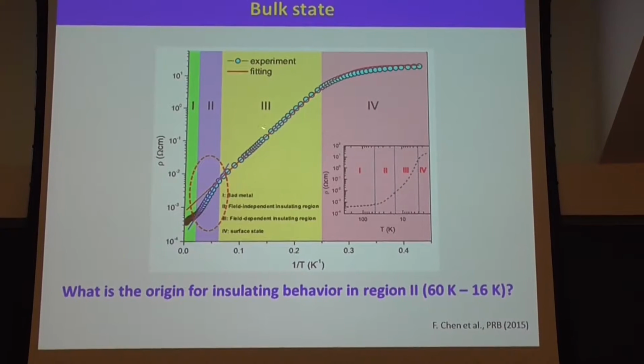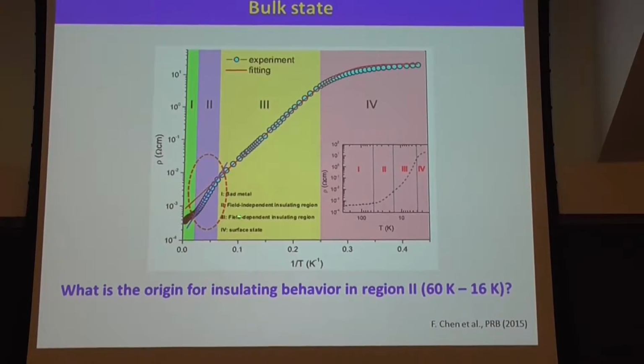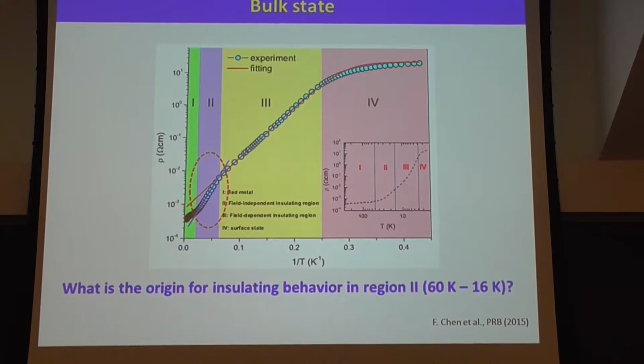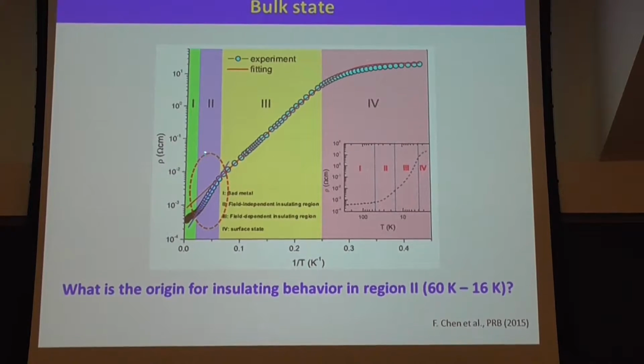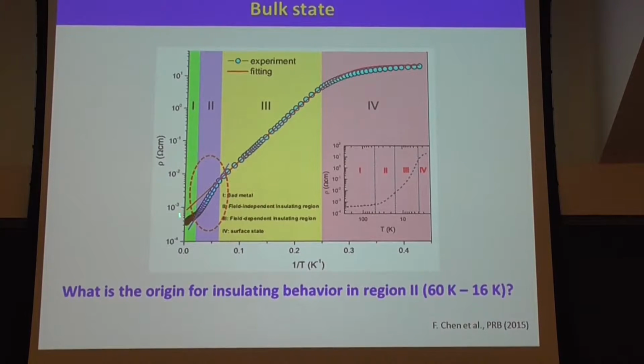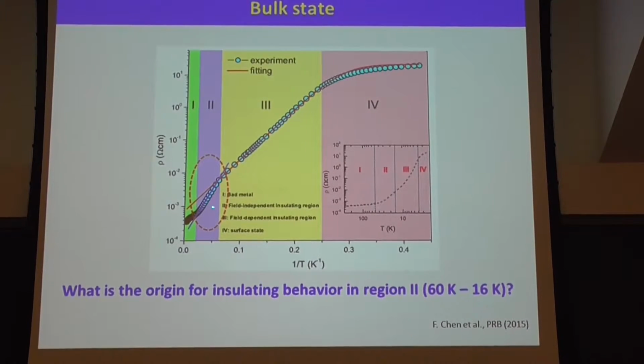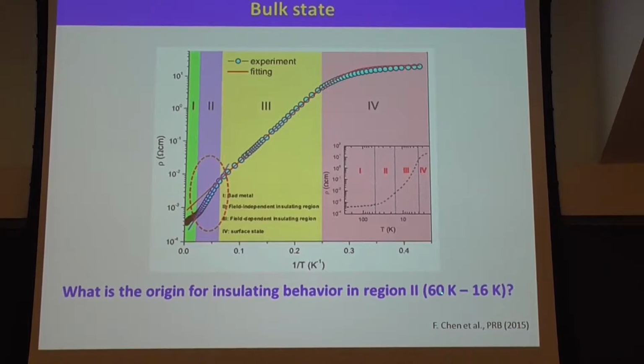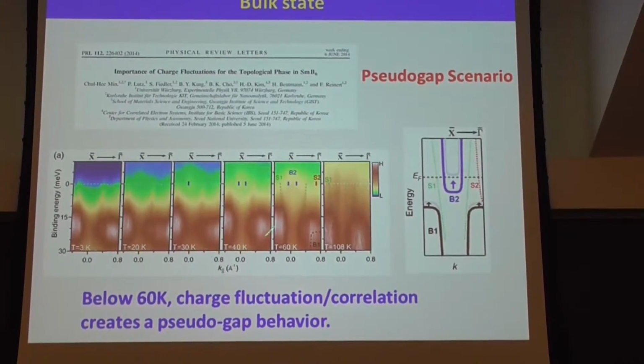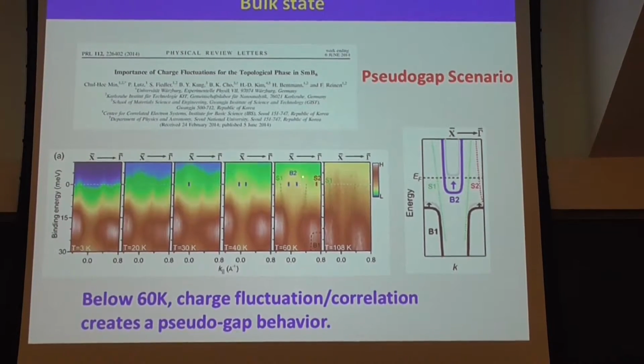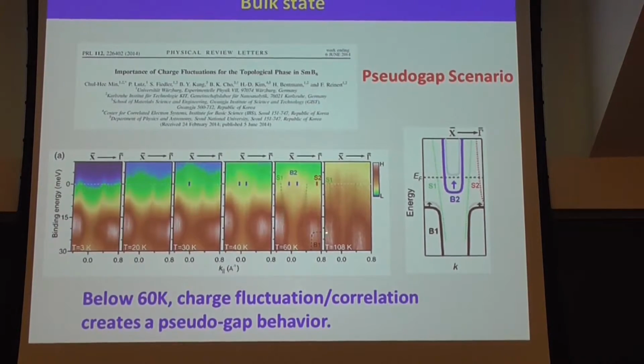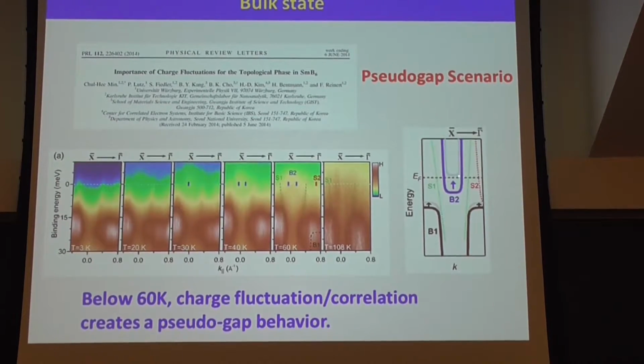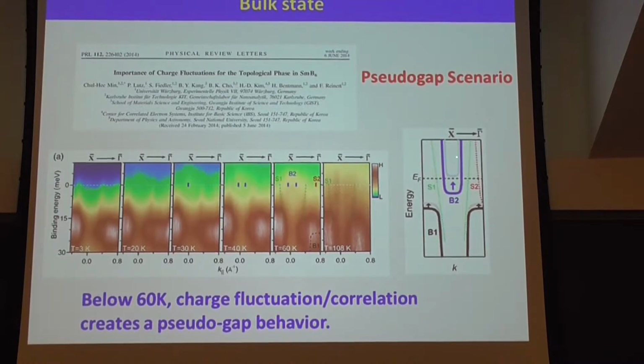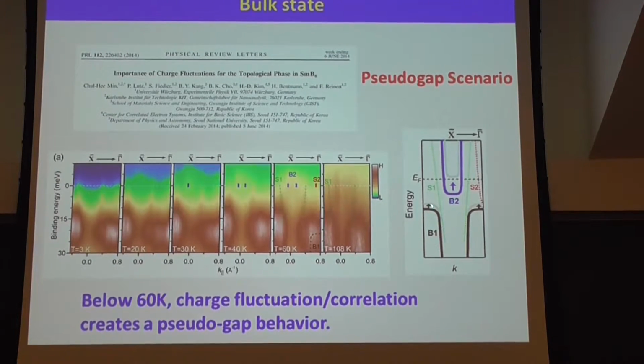But in this region, it means the field-dependent insulating region. This is like the Kondo gap. But this region, we want to talk about, is region 2, also insulating behavior, from 60 Kelvin to 16 Kelvin. Okay? Here some group reported by ARPES that from 60 Kelvin to 30 Kelvin, you can see this band is pushed up. And also a lot of bands are pushed up.